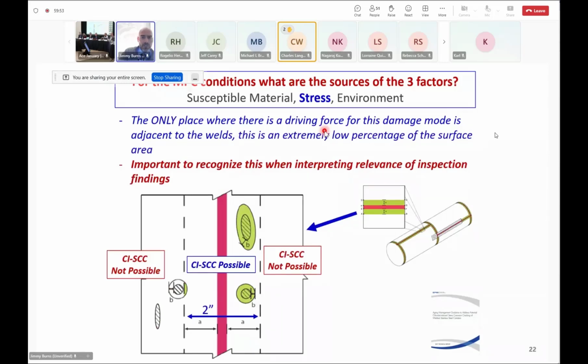And so it's really important to recognize this when you interpret the relevance of your inspection findings, because here's our weld region, right? It's kind of color coded here. And then this is expanded here. And these dashed lines represent that 2-inch example I just showed on the last slide. And the only place that CISCC is possible is in this region here. And so interpretation of the inspection results relative to where they are by these weld residual stresses is very important.